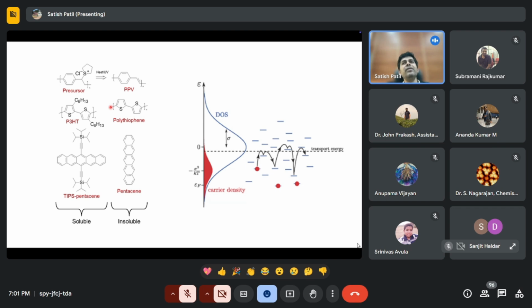You can't really make a very high molecular weight polymer and also make it very highly soluble. If the charge carrier transport properties of this polymer are very poor due to defects, then that polymer is not going to be a good polymer for making devices. So one has to optimize very carefully to increase the solubility without compromising the charge carrier transport properties of these semiconductors.